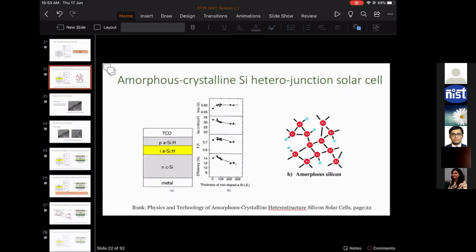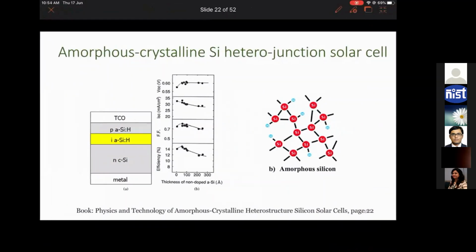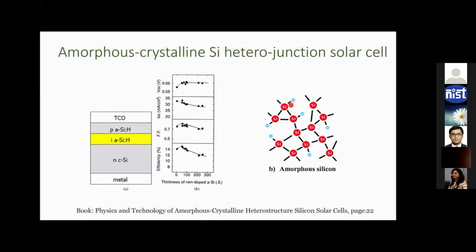What happens when light shines on it? Because of the heat or because of the internal dynamics happening inside your amorphous silicon, the hydrogen that is passivating the silicon dangling bonds, if you can see my screen, can now move across your silicon structure. And even at higher temperature, this hydrogen will break the bond and diffuse away from your amorphous silicon material.